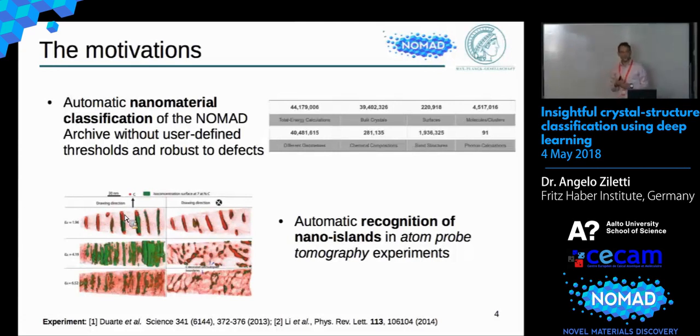These are complicated data, though, because for a data set you have hundreds of millions of data points. I think the record by the collaborator is 5.4 billion atoms in a sample. And so these are, of course, gigabytes of data. And the uncertainty of the position is very high. We don't know exactly where the atoms are, because these guys are looking at individual atoms, so it's kind of amazing that they can do something with that. But there's an uncertainty, a big one. And at least 20% of the atoms are missing. For the best detector in the world, 20% of the atoms are missing, because they're not detected.